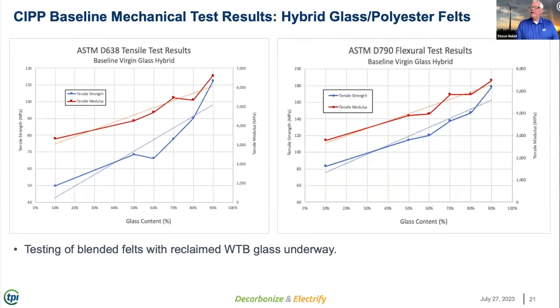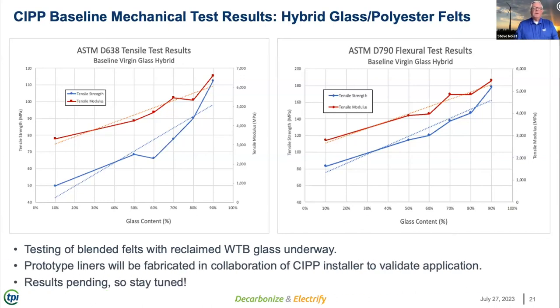Turns out when you hybridize like that, you can create tremendously improved properties, both in tensile and in bending. And as the level of hybridization goes up, the properties increase almost linearly. We're working today to find the sweet spot of glass content with felt content, but the result will be creating some liners and performing trial installations. With the improved properties, we reduce the amount of resin necessary and the thickness of the liner, both improving the economics, but also increasing the flow characteristics of the line.